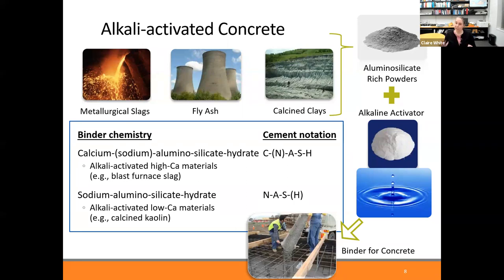So in terms of the gels that give the concrete strength here, there's once again this CNASH gel that exists, but that's only when you have a lot of calcium in your system. If you don't have calcium in your system, say if you've got alkali activated calcined clays, which are actually low in calcium, you end up with a different gel, which we call NASH. And so the question is, what impact do the different gels have on the performance of these concretes?